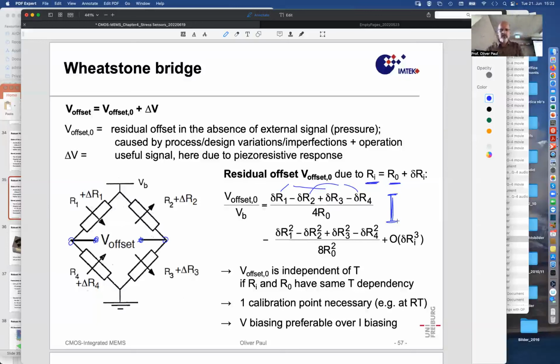Okay, so in this case, of course, for the calibration, it's much easier to have a linear sensor, and again, it's much better to drive these sensors under V biasing, applying a voltage rather than a controlled current, because we have this ratio of resistances, and then the change of the resistivity with temperature is kind of compensated in this ratio. And the only thing that remains is actually the temperature coefficient of the piezoresistance. Yeah? That is not compensated in any scheme. That needs to be compensated differently.